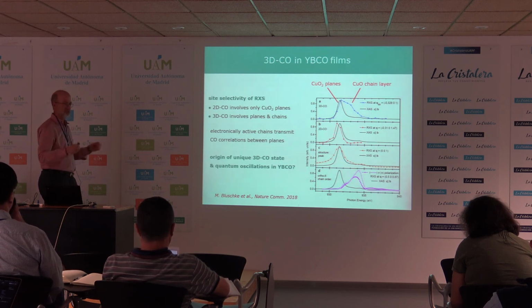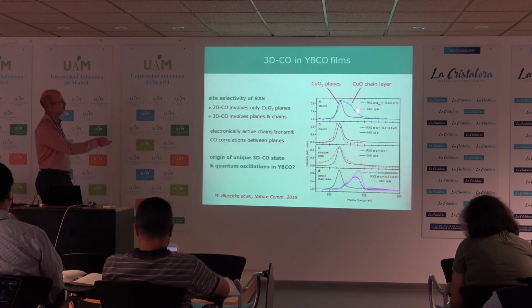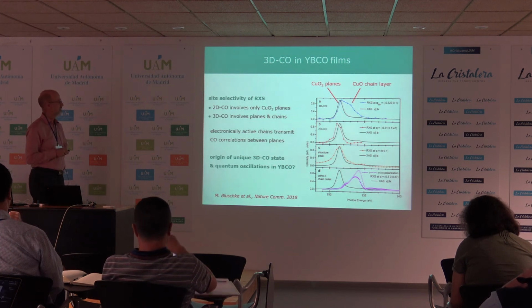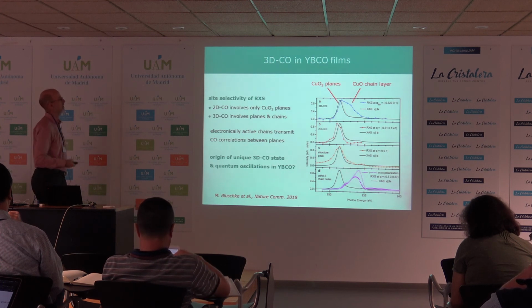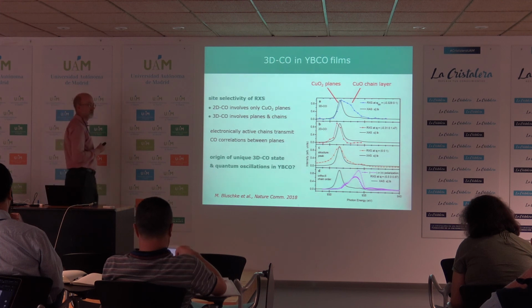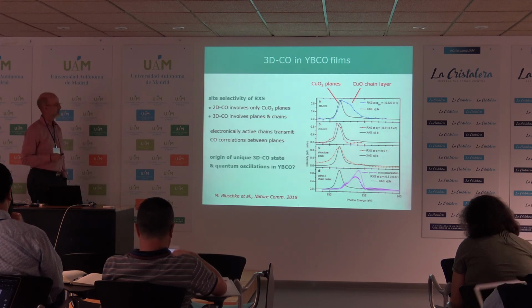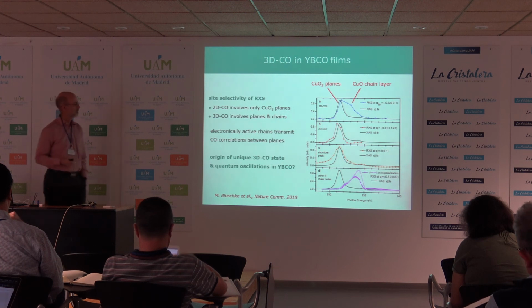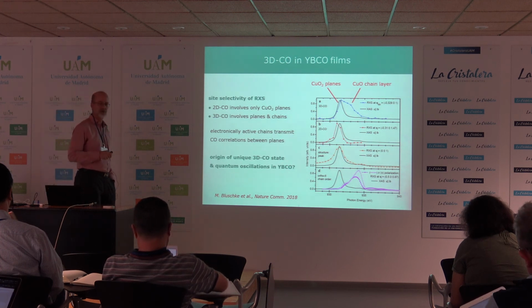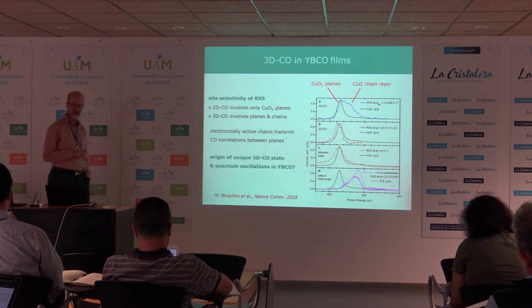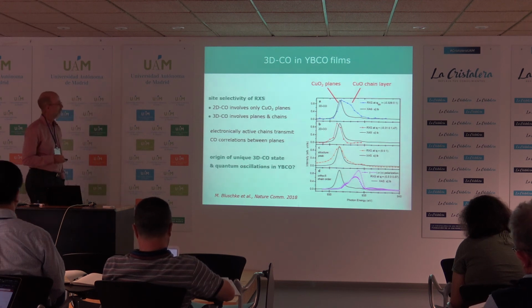So we can do site-selective resonant X-ray scattering. And this 3D charge order actually has both components. So both the chains and the planes are participating. Right? So the chains in the YBCO structure participate in the three-dimensional charge order. They communicate information between the copper-oxide planes, and that may be the reason why this three-dimensional charge order state is particularly stable in the YBCO structure.